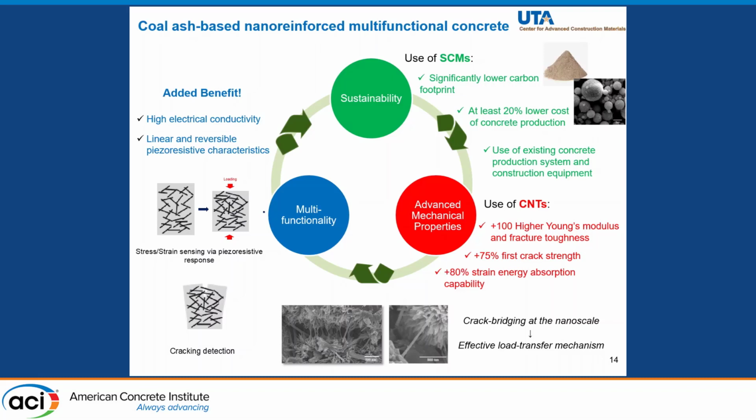Though, owing to their unique properties, CNTs impart new functionalities to the cementitious mortars. Due to their high electrical conductivity, they can increase the electrical conductivity of the cementitious mortars, which are ordinarily insulators, and they can also improve their stress, strain, and crack detection ability.